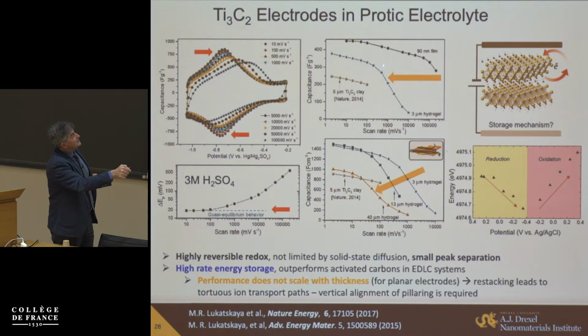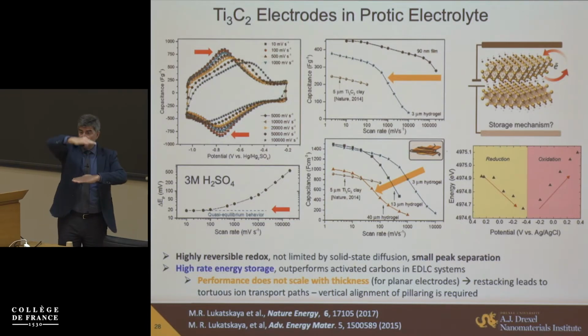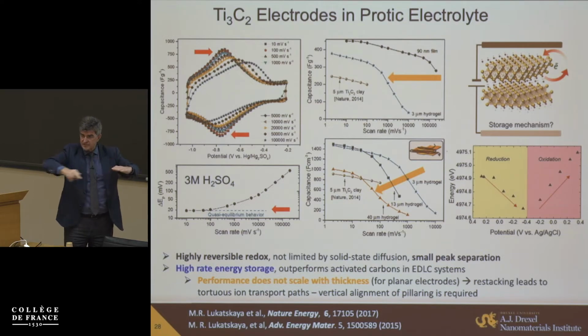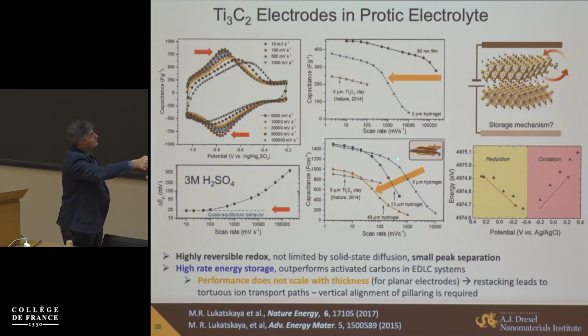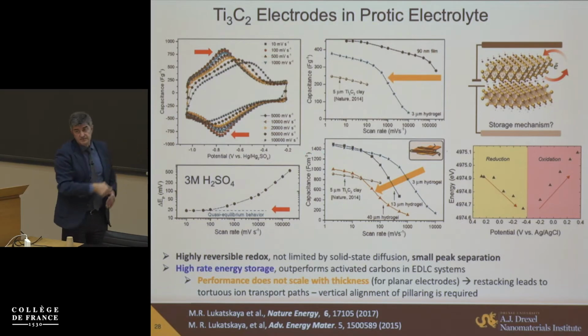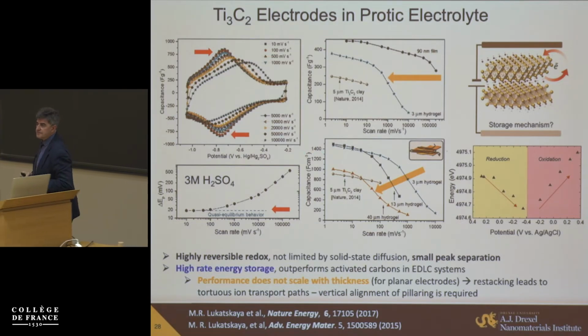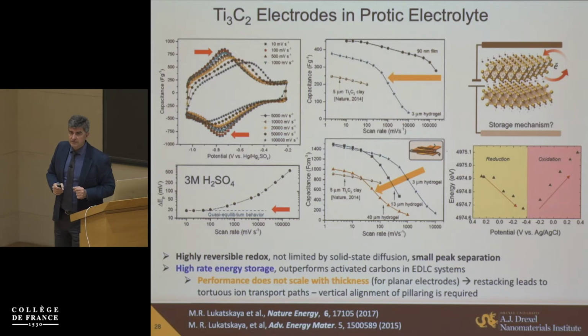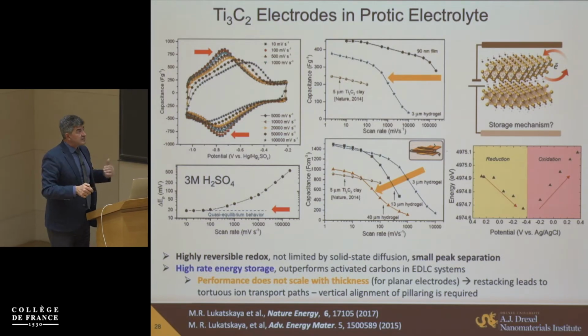But you go to 3 micron, 5 micron, and they're all aligned this way in this case, specifically so the diffusion path increases much longer, and you see we start losing capacitance. We still can get extremely high rate for even few micron gel electrodes, like 1500 farad per cubic centimeter, which is several times more than one would get on carbon here. But there is this limit.